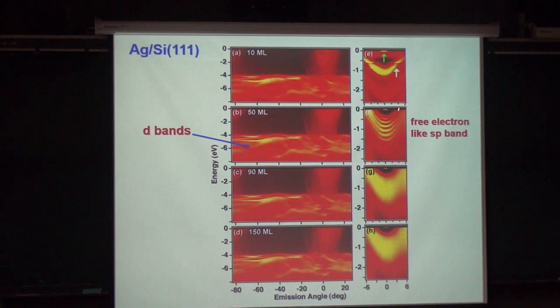You go to 50 layers, the substrate effect becomes less, and you got this sp band here. But you look deeper also, this corresponds to that one. So you look deeper, you got this whole bunch of stuff here. Those correspond to D bands. So you can see the SP band, free electron like, you get D bands deeper. And eventually, when you get thick enough, all gets smeared out into bulk crystals. So the 150 layers is simply a single crystal. You cannot see the discreteness of the system anymore.